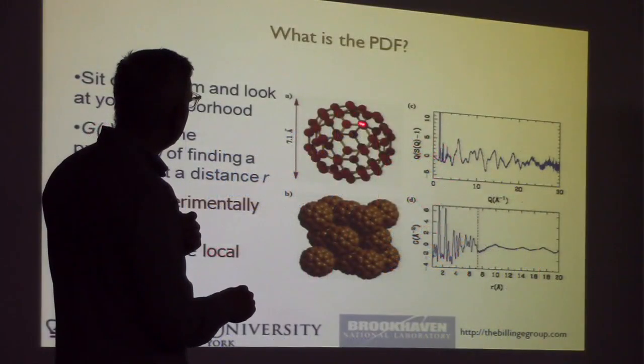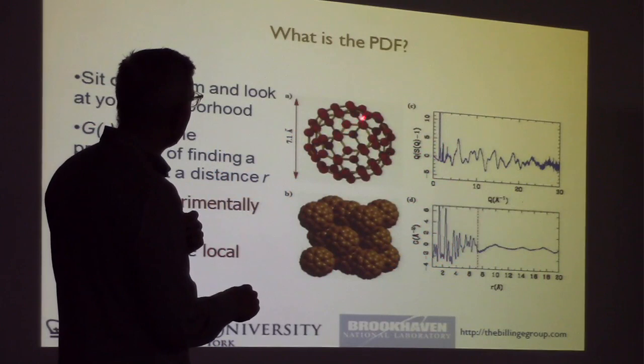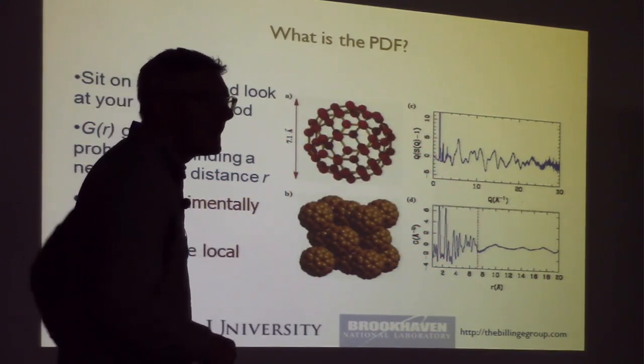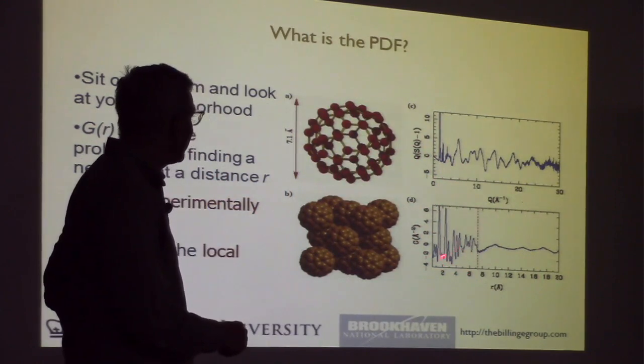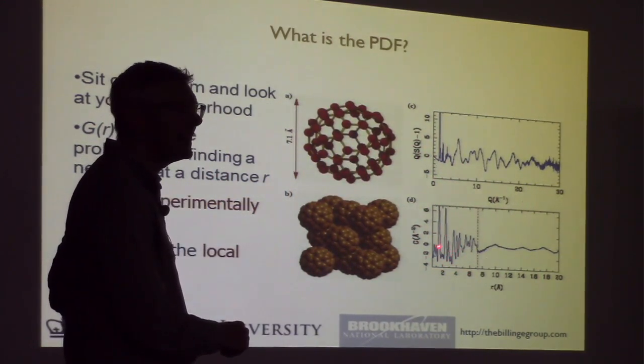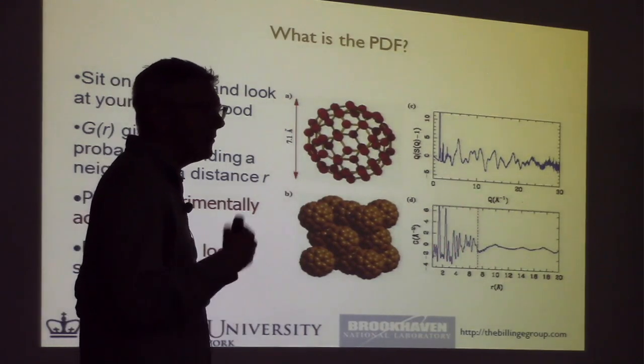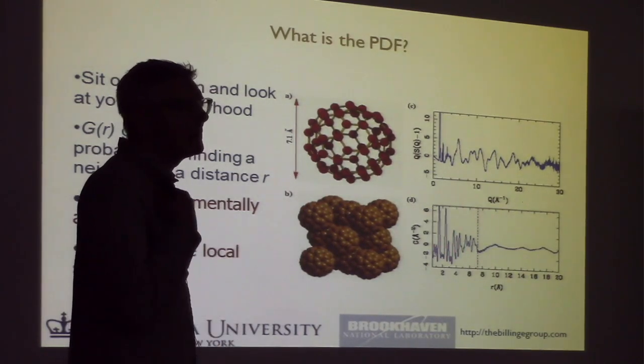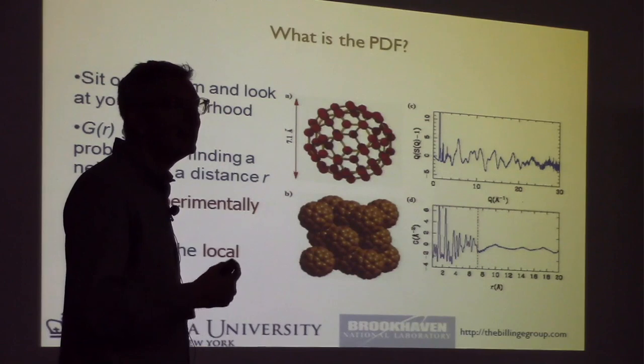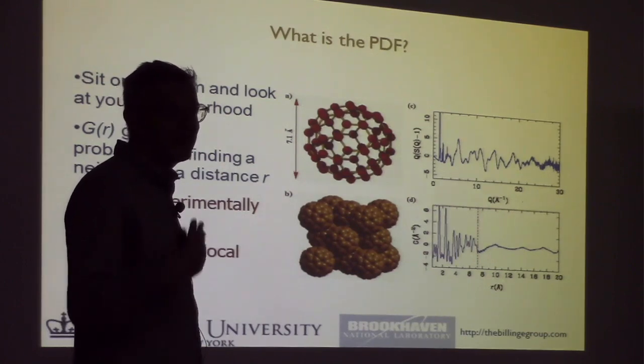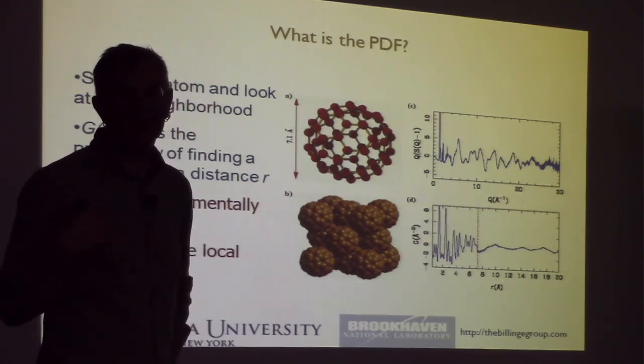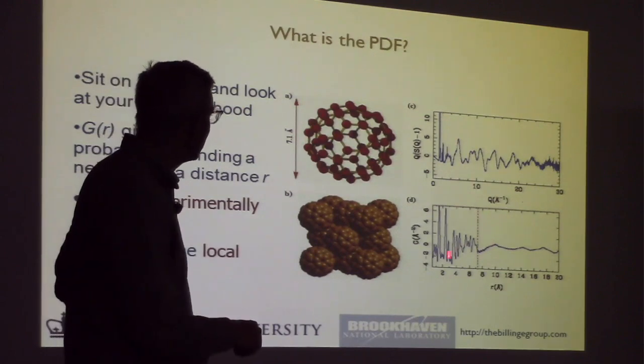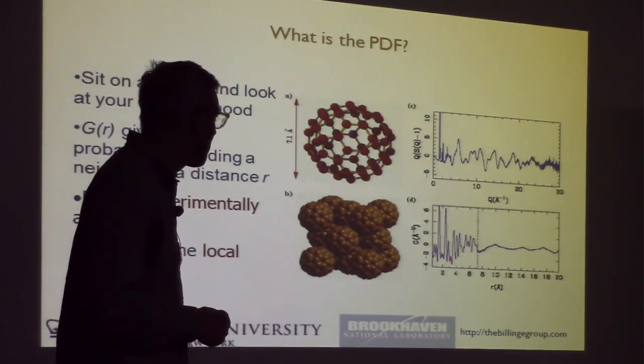The pentagon has the near neighbor distance, and it has the second neighbor distance, but it has no third neighbor distance. So intuitively, you look at the intensity of that third peak and the ratio of the intensity to the second peak, and you can deduce ring statistics in your carbon material. You can tell how many five-member rings versus six-member rings. You can do that without even doing any modeling. You just look at the relative intensity of those two pieces.